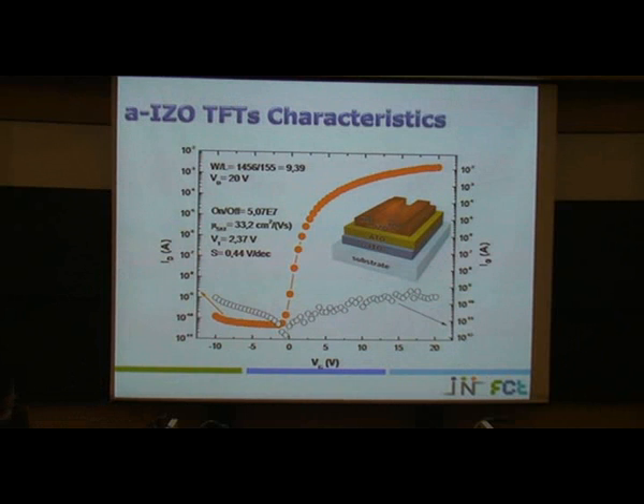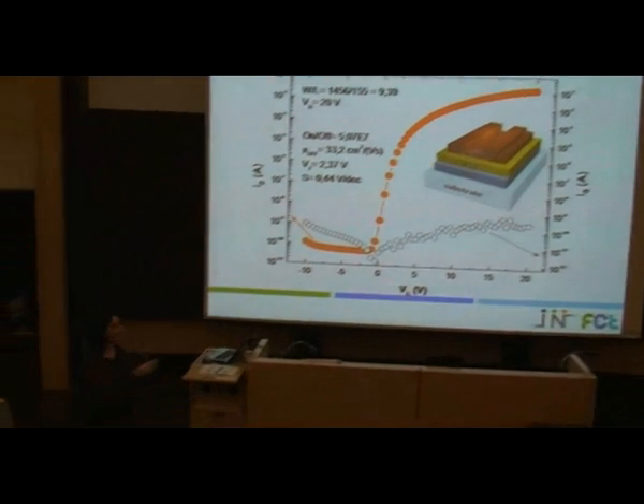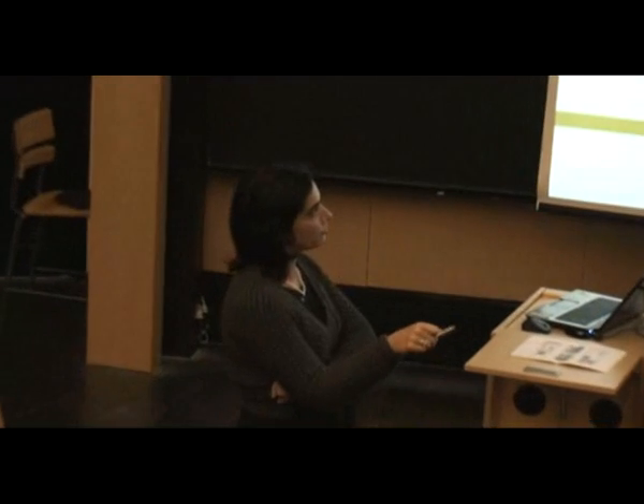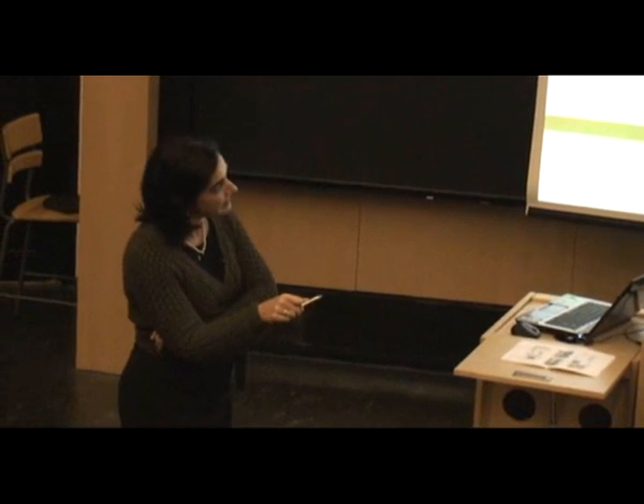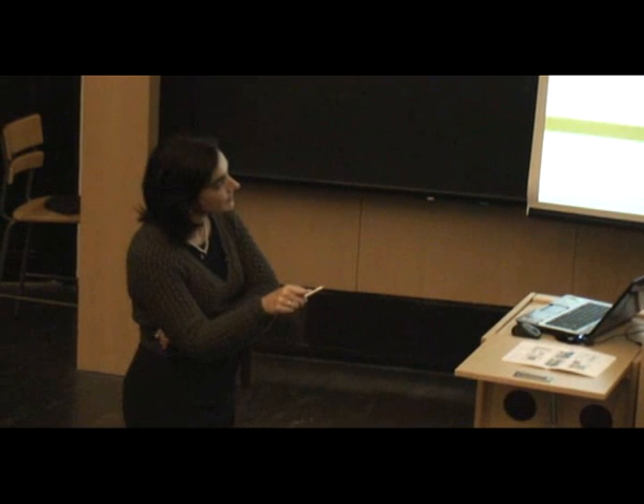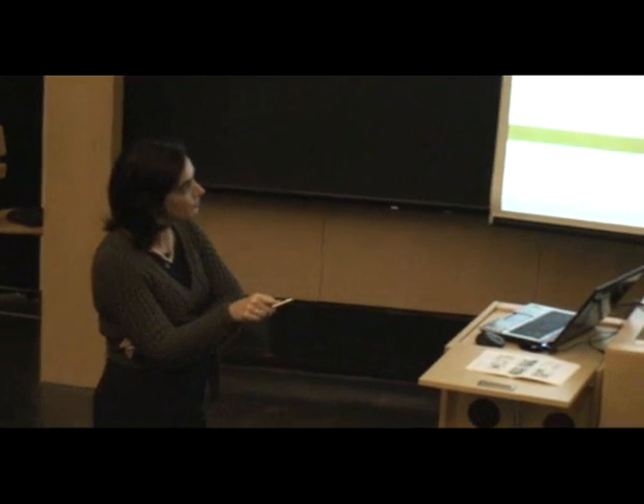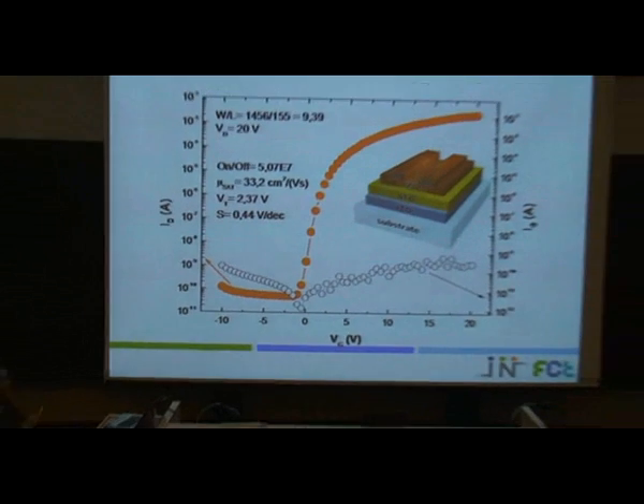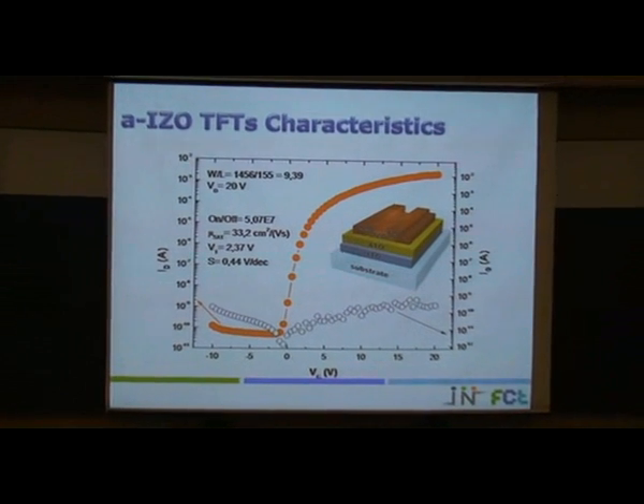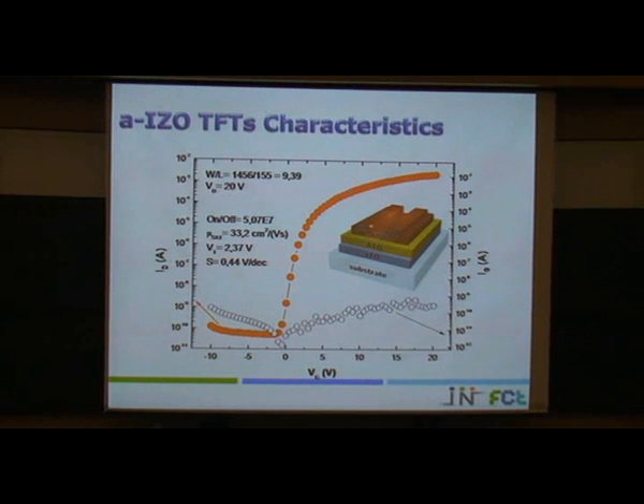Concerning the devices based on amorphous indium zinc oxide, this is very interesting because, as I told you, we are using the same material for different applications, for TCOs or for semiconductors. For example, here is a typical structure for a TFT with the IZO as the channel layer, and for source and drain we are using also IZO. So this is the substrate, the bottom gate, ITO, the dielectric layer, ATO. This is a multi-layer structure with alumina and tantalum oxide. And for the channel, for the semiconductor and for the source and drain, we are using both IZO.